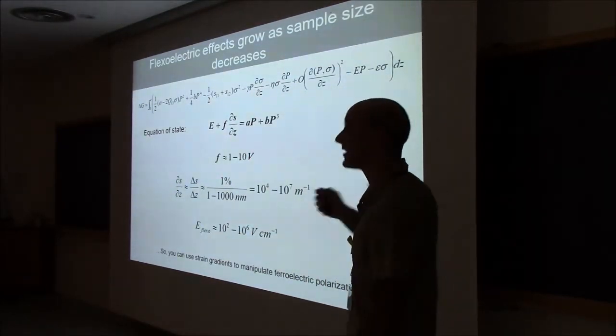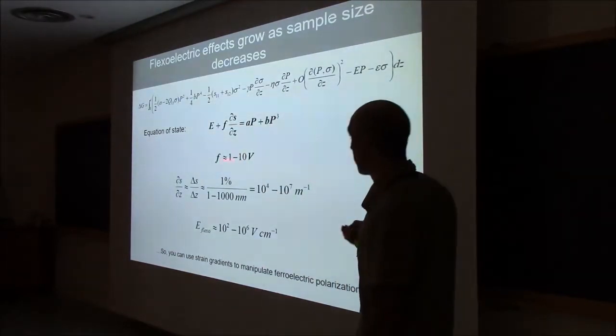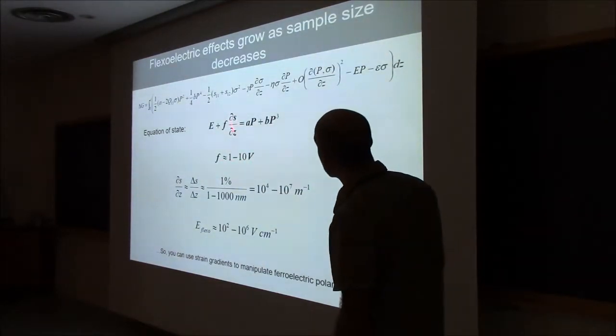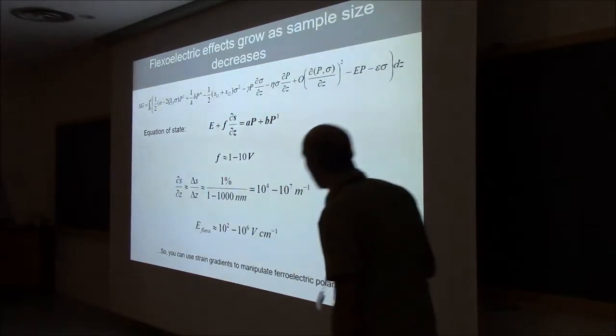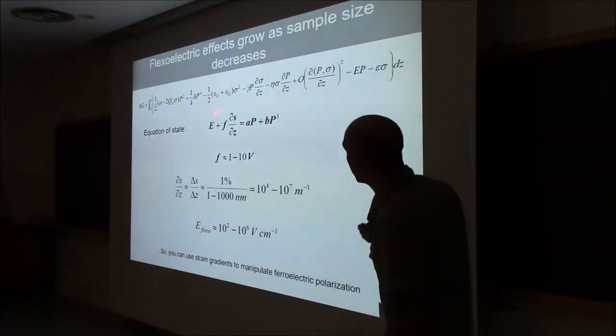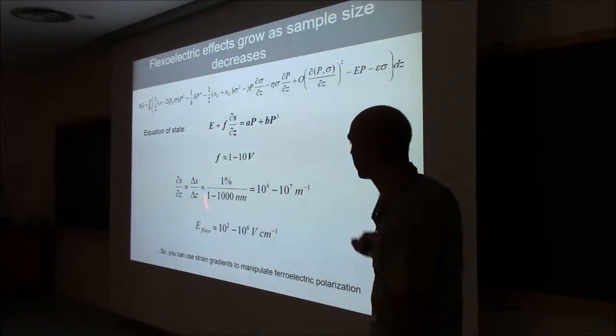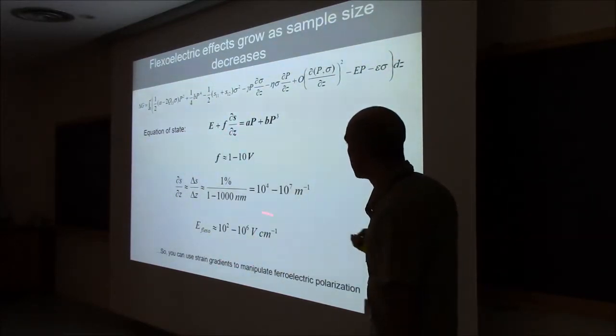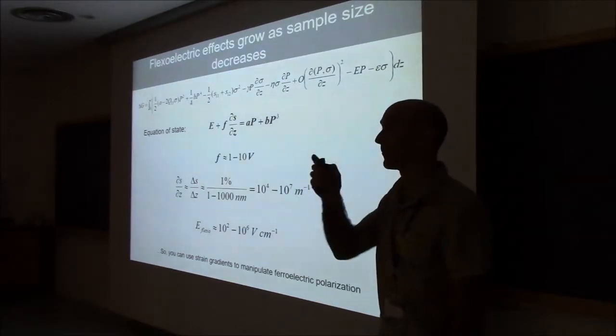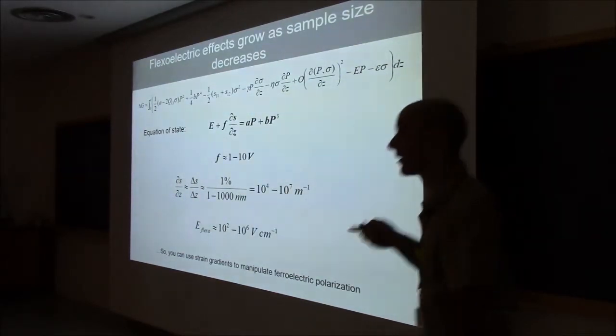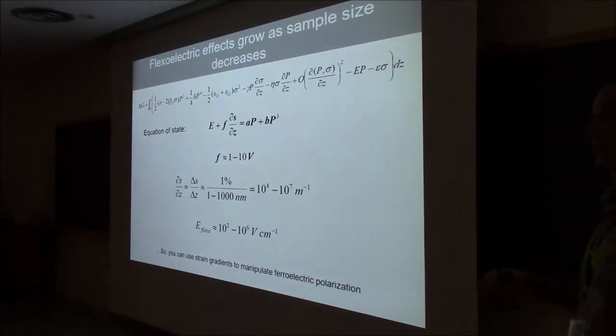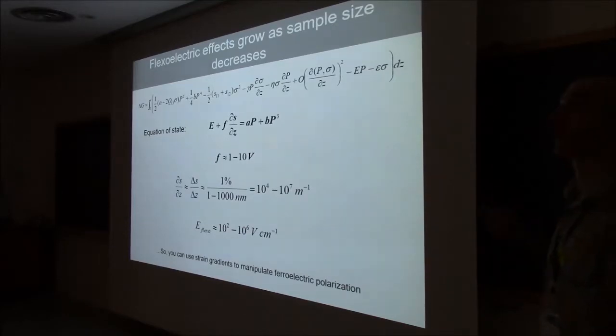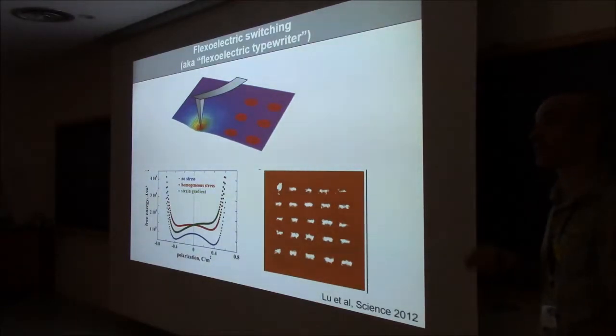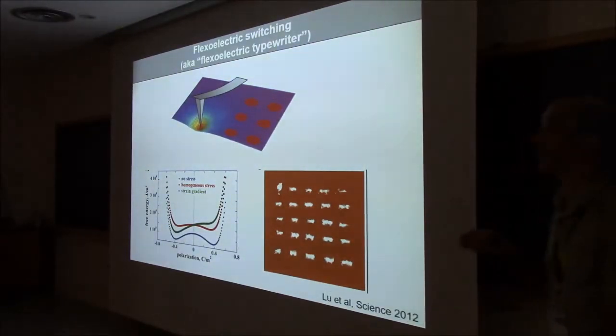Now F here is a flexo voltage coefficient, which is, remember, of the order of about 10 volts. This is the strain gradient, which at the nanoscale is about this number. So this effective flexoelectric field, this thing that behaves like an electric field, is of the order of between 100 and a million volts per centimeter. Big. A million volts per centimeter is big, by definition of million. In fact, it can be bigger than the coercive field of your ferroelectric material, which means that you can use strain gradient to switch the polarization.